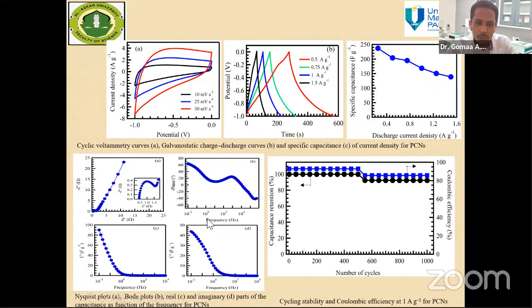And this is the Nyquist plot or impedance spectra showing a highly conducting material, which shows a resistance of around 0.0 ohm, which we call solution resistance, and charge transfer resistance around 1 ohm, indicating this is a very conducting material. And stability also, we have tested this material up to 1000 cycles. So it shows more than 95% of its original capacitance value, even after 1000 cycles of using this device.